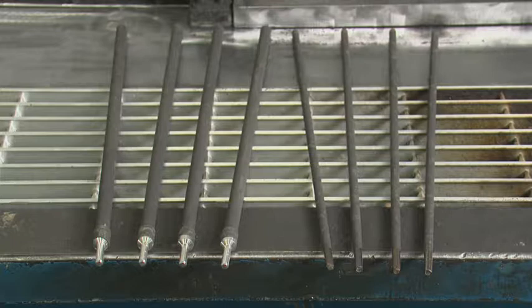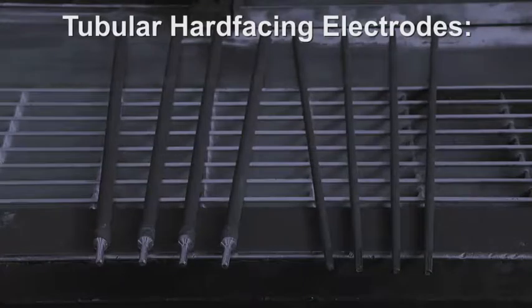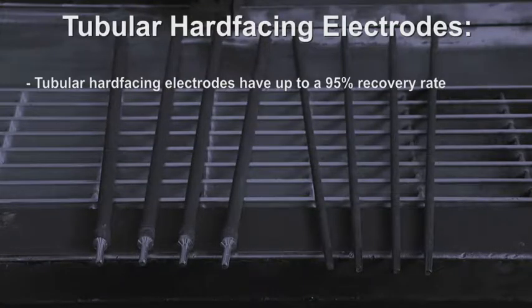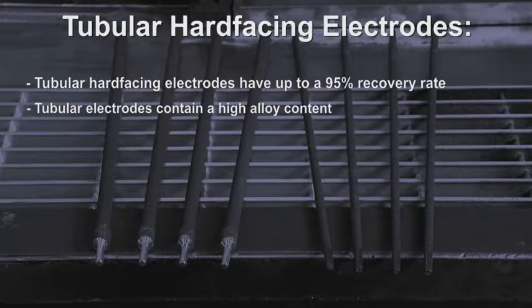Here are the advantages of tubular electrodes. Tubular hard-facing electrodes have up to a 95% recovery rate. For every 10 pounds you buy, up to 9.5 pounds are deposited to the part, with very little waste. Tubular electrodes contain a high alloy content.